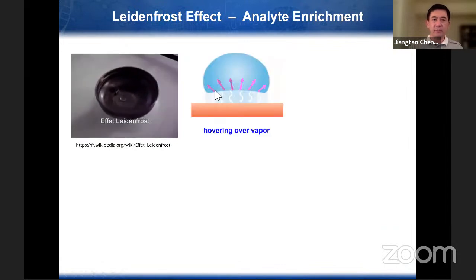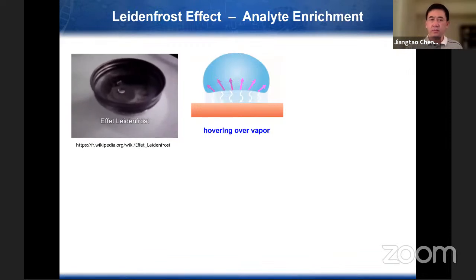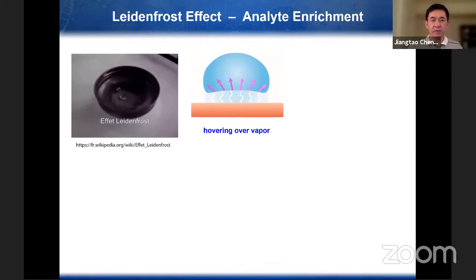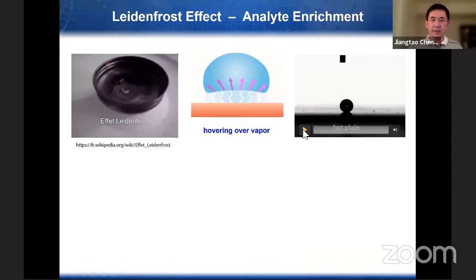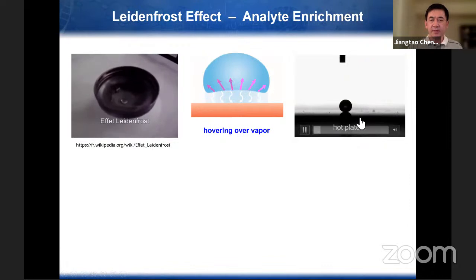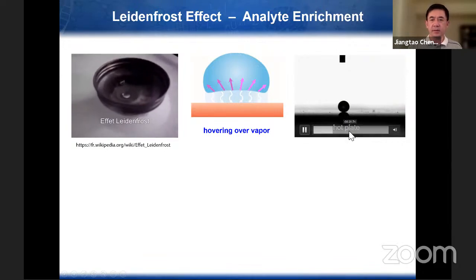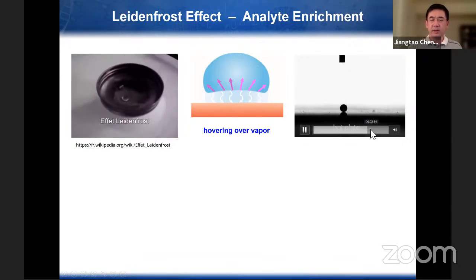And then we applied the Leidenfrost effect. The Leidenfrost effect means if we put droplets on a hot surface, the formed vapor layer can make the water droplet hover over the vapor layer. And this is an example showing the Leidenfrost effect. And this is the hot surface. So we can see the evaporation of the droplets on the hot plate actually leads to a relatively fast